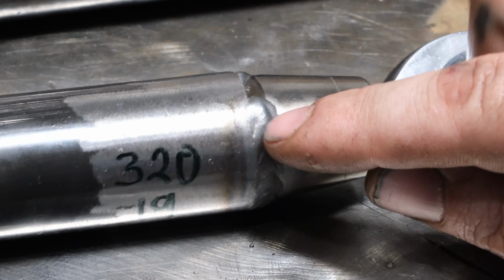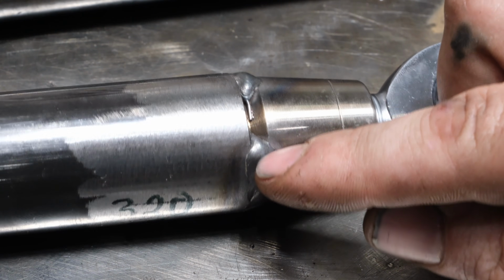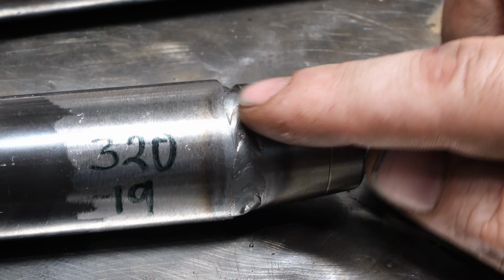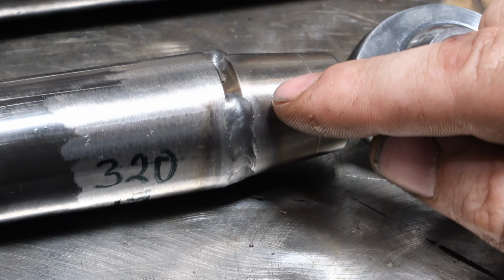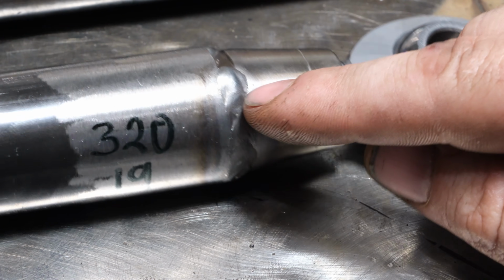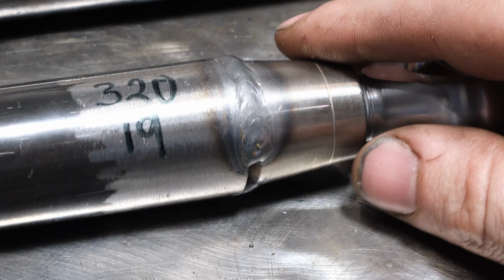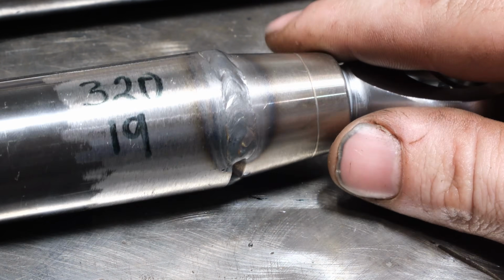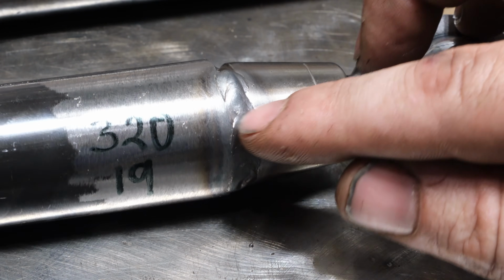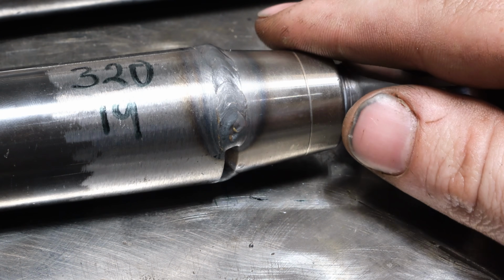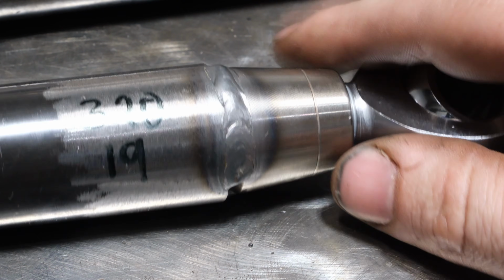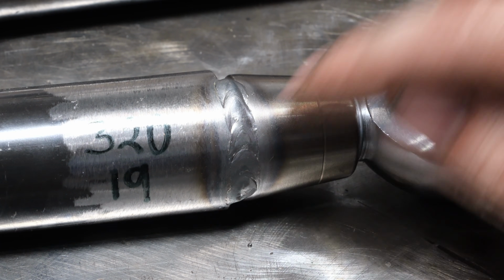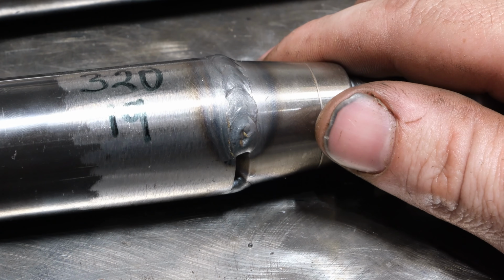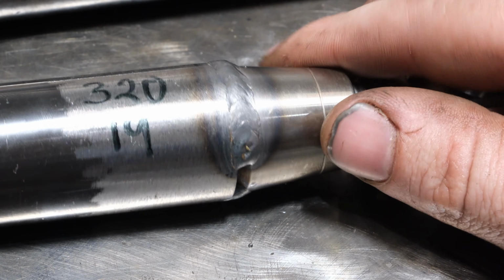I like that. The beginning of the weld, or what looks to be the beginning, is a little bit humped up. Adjusting my run-in speed as well as some other parameters would likely help that. But overall, this is a decent looking weld. I could have slowed down a little bit, which I did here, and it would have improved a little bit of the, not cold toes, but it's not quite wetted out there. So little small improvements would make this a lot better.